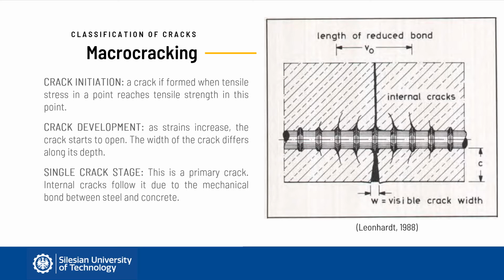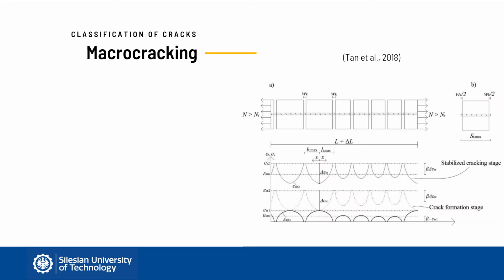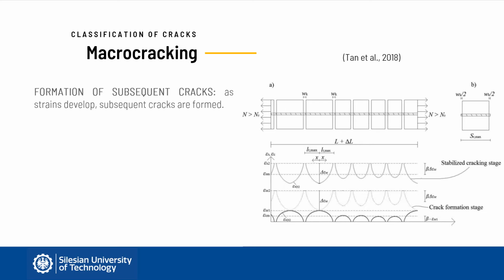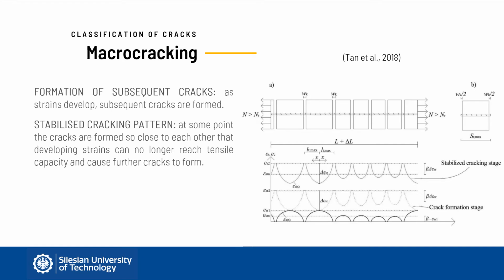Such a crack is the primary crack. It is followed by internal cracks which are formed due to activation of the bond between steel and concrete. As strains develop further, subsequent cracks are formed. At first, each crack is in a single crack stage, and there is no impact of the cracks on one another. At some point, however, the cracks are formed so close to each other that developing strains can no longer reach tensile capacity and cause further cracks to form. This stage is called stabilized cracking stage.